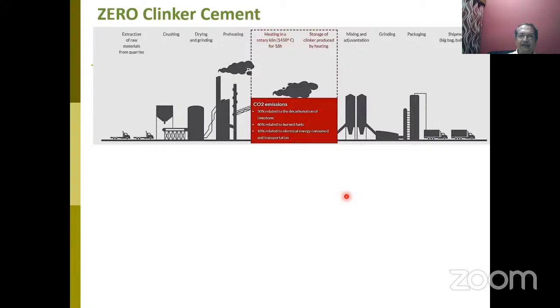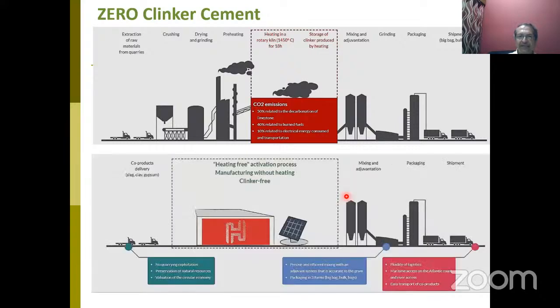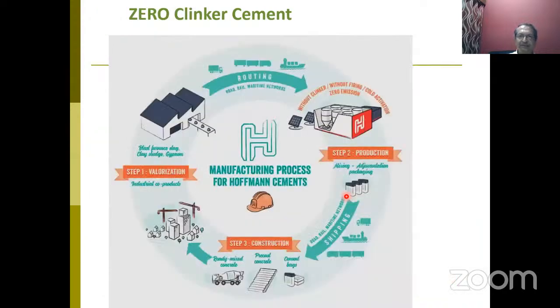And there are other approaches which many companies are using. This is another approach of heating. The portion which heats the clinker to 1450 degrees centigrade is the one which they are attacking, and they are trying to see whether we can do a heating-free activation process by alkalis and things like that, so that we avoid that heating process and also reduce all the attendant carbon dioxide emissions and so on.